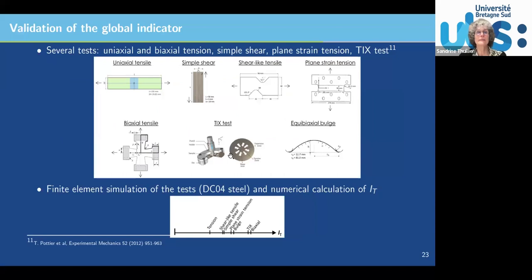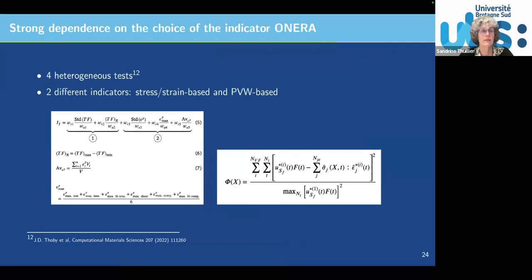And what was performed was a comparison of several heterogeneous tests. You've got here shear, uniaxial, biaxial, this one I've shown you which is a forming type, bulge, plane strain. You see all these tests that we know. We can rank them using this global indicator. The idea was, we know these tests more or less, so which one is the best one? Maybe we know that this one seems to be quite complex, and biaxial is still a good one. In this ranking, we can see that biaxial is maybe one of the best. So the idea is to define an indicator in order to rank and then help you to choose the best test.